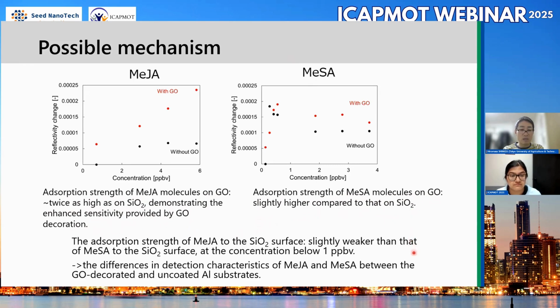So the adsorption strength of methyl jasmonate to the SiO2 surface is slightly weaker than that of methyl salicylate to the SiO2 surface, at concentrations below 1 ppb. So you can see the difference in detection characteristic of methyl jasmonate and methyl salicylate between the graphene oxide decorated and uncoated aluminum substrate.